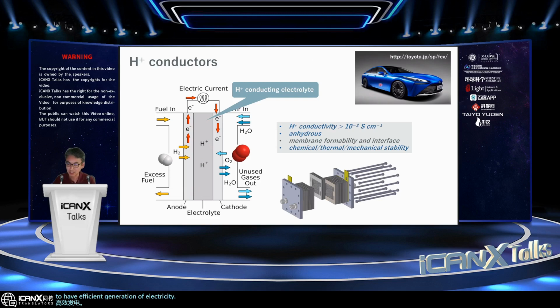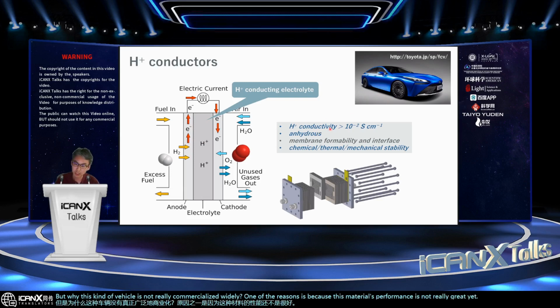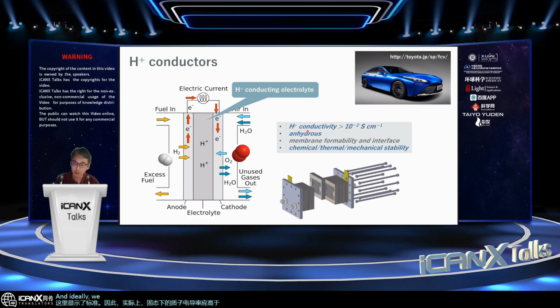But why is this kind of vehicle not really commercialized widely? One of the reasons is that the performance of these materials is not really great yet, and the criteria are shown here. The proton conductivity in the solid state should be higher than this value. And ideally, we shouldn't need humidity management, which means anhydrous conditions, while still having a very high proton conductivity